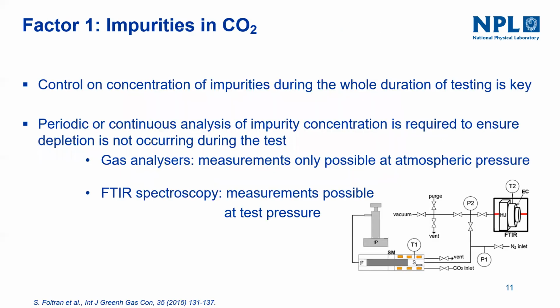So one is that the concentration of impurities is very key during the whole duration of the testing. In the CO2 stream there is continuous replenishment of the impurities, because there's a continuous flow. But in normal testing, there could be a depletion of the impurities. So we need to control the concentrations, which can be done by periodic or continuous analysis of the impurity concentration during the testing. One option is gas analysis measurements, but the issue is that it is only possible at atmospheric pressure.